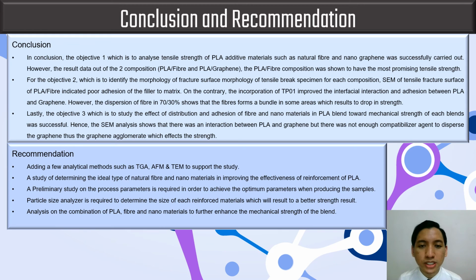However, the dispersion of fiber in 70-30% shows that the fibers form a bundle in some areas, which results in a drop in strength. Lastly, objective 3, which is to study the effect of distribution and adhesion of fiber and nanomaterials in the PLA blend toward the mechanical strength of each blend, was successful. Hence, the SEM analysis shows that there was an interaction between PLA and graphene, but there was not enough compatibilizer agent to disperse the graphene. Thus, the graphene agglomerates, which affects the strength.